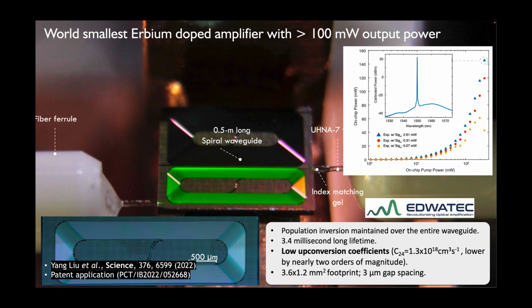And what this allows us to make is very compact amplifiers. So it shows an amplifier here, it's a spiral that's 50 centimeter long. The chip here is 5 millimeter in diameter. And we get optical powers here that are more than 100 milliwatts. And so that's really comparable to what you can obtain with a small benchtop optical fiber amplifier. So again, we are now nearing a performance level that becomes interesting already for systems.